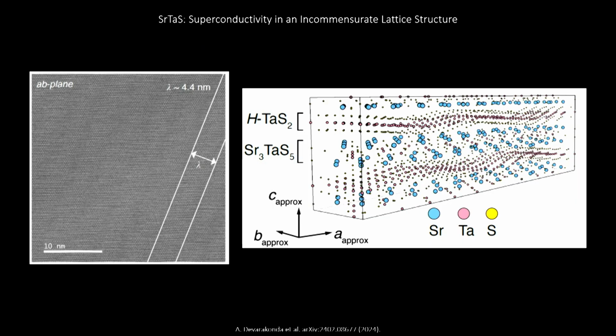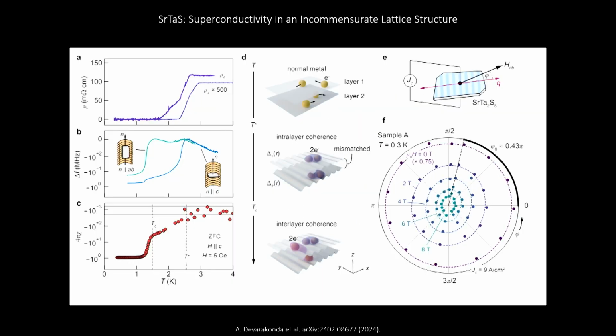This is strontium tantalum sulfur. This is a compound that was posted on arXiv a couple months ago. The idea is that this material has a very long wavelength incommensurability, not unlike something found in other incommensurate lattices like the high temperature copper oxide superconductors. So you see this rumpling of the superconducting layer in this lattice in a way that influences transport phenomenology. So here, maybe focus on this plot particularly.